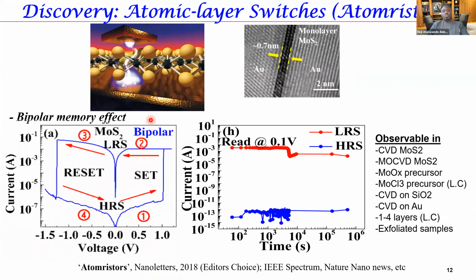So lo and behold, Rui Jing was actually very successful. After 6 months she showed fantastic results. This is a monolayer of MoS2 between 2 gold electrodes. We use gold to rule out metal oxides that can form for non-noble metals, which could also produce a memory effect, so we had to stick to noble metals. And then you see these characteristic electrical current versus voltage curves of these vertical structures.